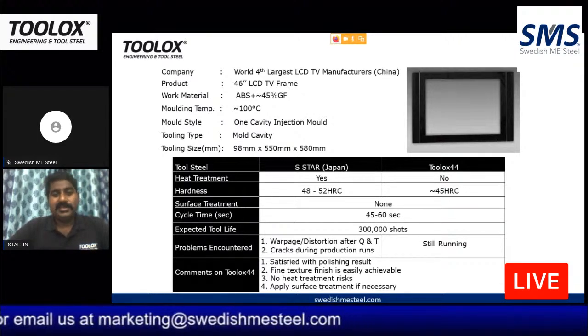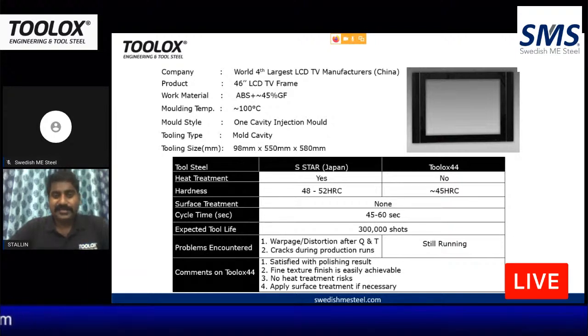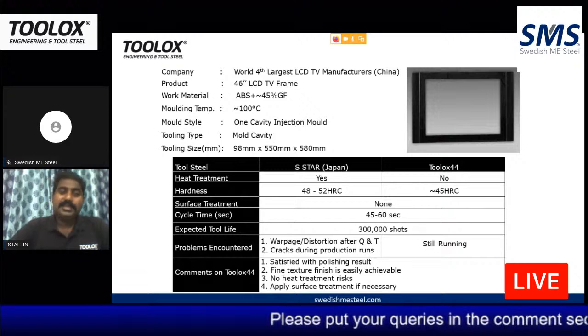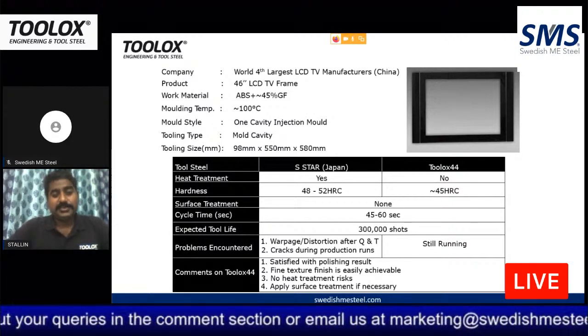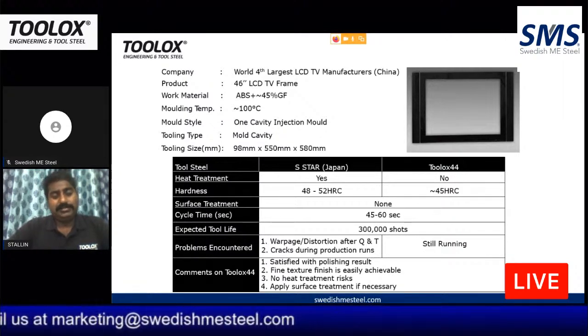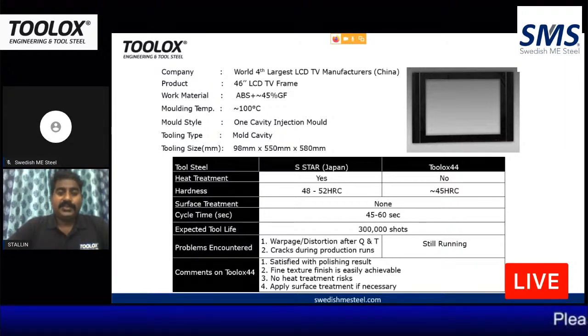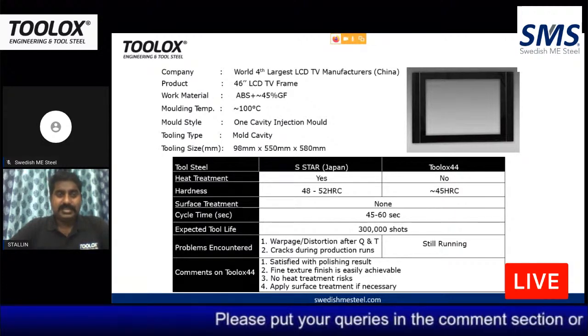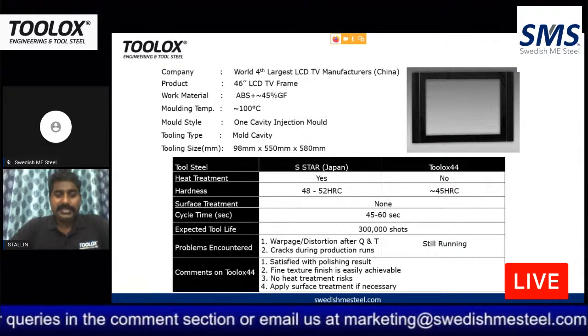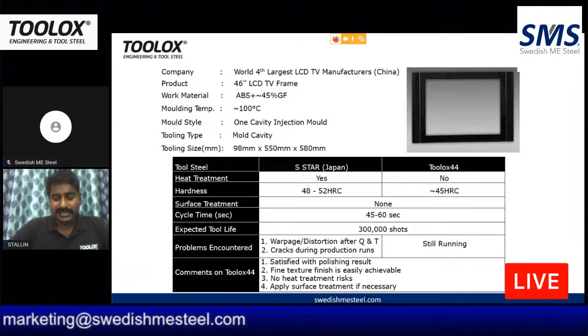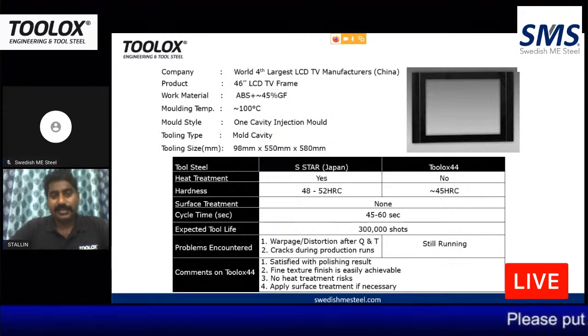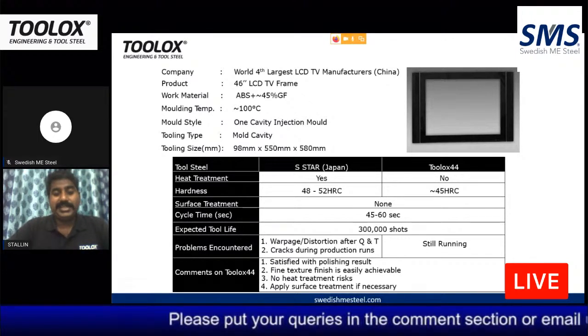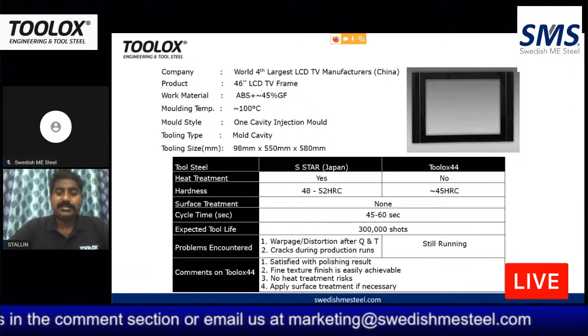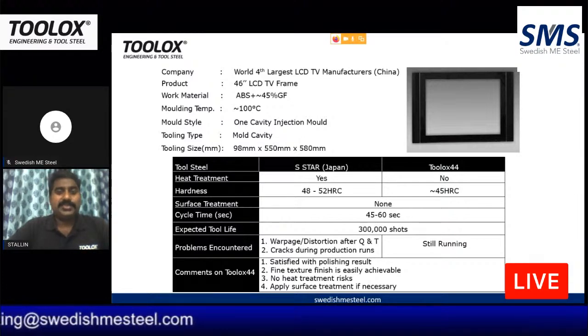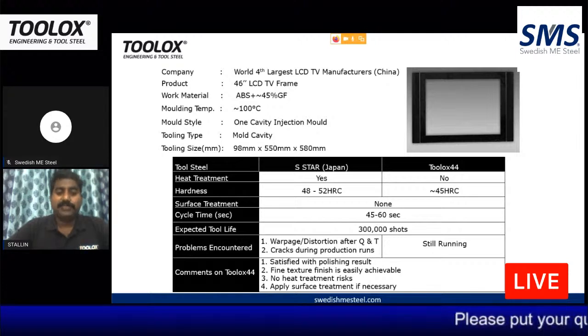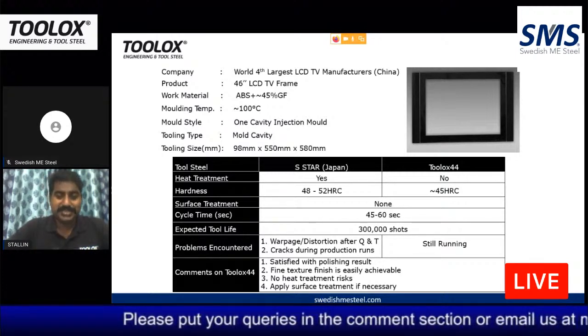The working material is ABS with 45% glass filled. So the customer has previously used S Star, which is again a patented material just like Toolox, but that has not been in pre-hardened version. So they machine it and do heat treatment just like any other hot working steel. But with Toolox 44, there is no heat treatment involved, directly machining and put into use. So 45% glass filled material, and you can see the tooling size relatively higher, 98 mm into 550 by 580. So they were facing issues of warpage and distortion after quenching and tempering after heat treatment. And they also saw cracks being initiated during production runs. So all those issues we solved using Toolox 44, and the customer is very much satisfied with the polishing result, the fine texture finish that Toolox gave, and obviously they didn't face any heat treatment risk, which is not required with Toolox.